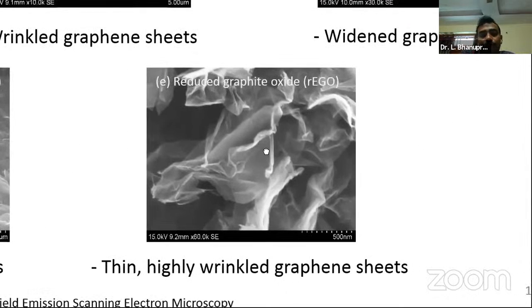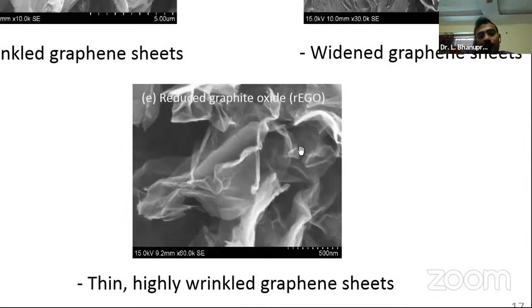When it is reduced using the strong reducing agent like hydrazine hydrate, all the oxygen groups are removed. As a result, these stacks of sheets are further broken into a very few number of sheets, like 5 to 8 sheets combined, or sometimes a single sheet can be noticed. Here you can see a beautiful transparent graphene sheet, with the edges folded, and here I can clearly notice my graphene flakes, right?